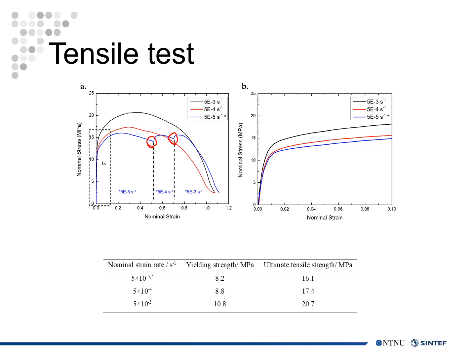When we change the strain rate from 10^-5 to 10^-4, the stress level also goes a little bit higher, and these two curves meet each other. This is the same when we change from 10^-4 to 10^-3, then these two curves also meet each other.